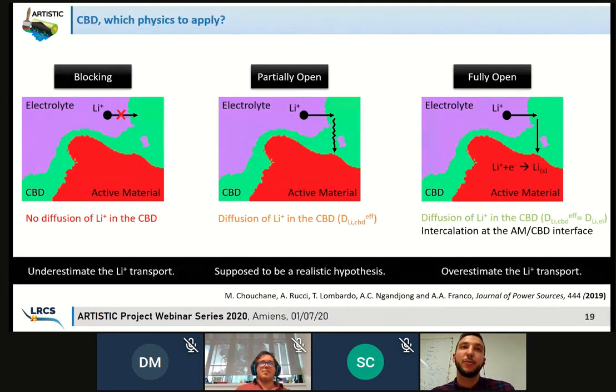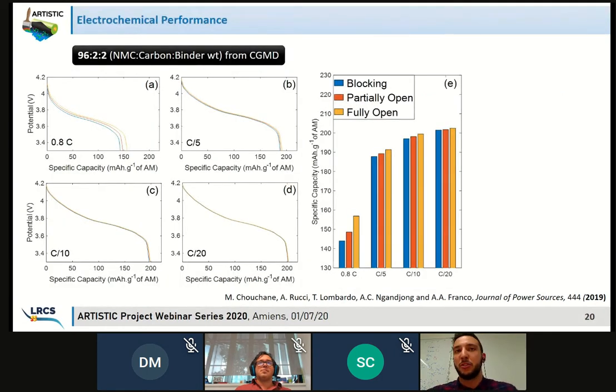So obviously, the first assumption will highly underestimate the lithium transport, because we know from experimental point of view that we have microporosity, which allows transport of lithium ion. The second one is supposed to be the more realistic one, because the last will for sure overestimate the lithium ion transport. So let's see, here are the results when we applied it to 96:2:2 electrode of NMC, which was